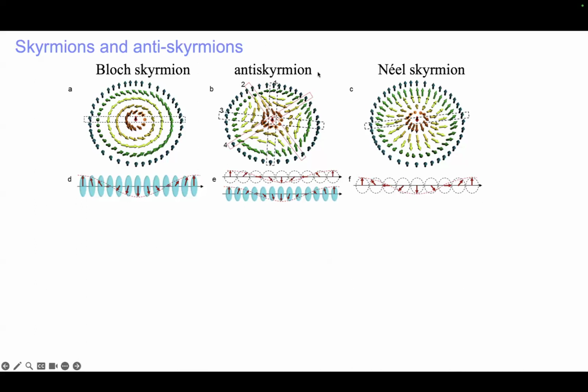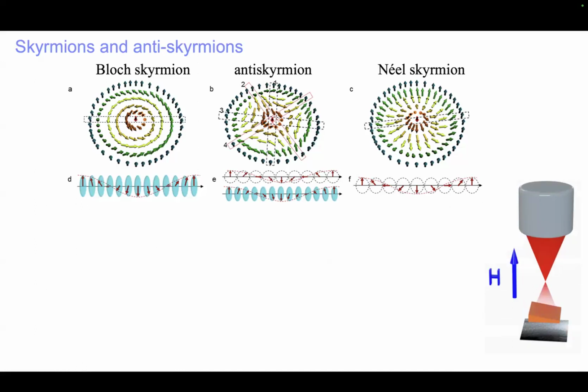And in the middle, you can see what's called an antiskyrmion. It turns out that if you have a low symmetry magnetic material of a certain type, then the Dzyaloshinskii-Moriya exchange interaction changes sign along different directions in the crystal structure. And this leads to a boundary in which some parts are Néel-like and some parts are Bloch-like. And as you go around the circumference, you rotate from a Néel-like to a Bloch-like structure, changing also the chirality. So how do you detect these objects? You typically detect them in a transmission electron microscope. In this case, we would take a single crystal and cut a flake which is thin enough to be electron transparent.